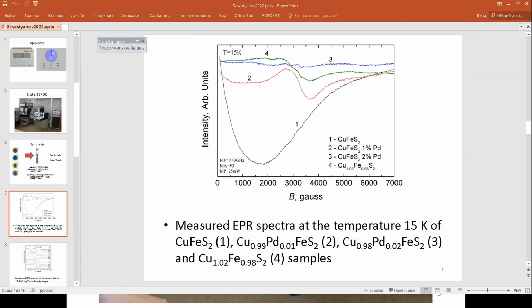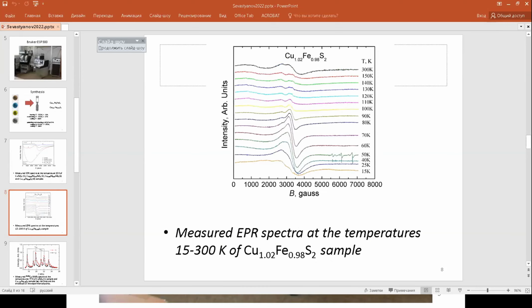A distinctive feature of the CuFeS2 sample is the presence of an intense EPR signal with a wide anisotropic line shape over the entire range of the studied temperature, presumably having a ferromagnetic nature. Also in the temperature range of 100 Kelvin to 130 Kelvin, there is a rapid change in the signal parameters, which indicates the possible presence of a structural phase transition.